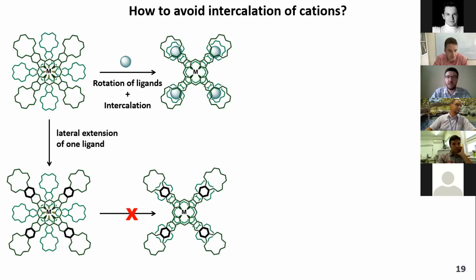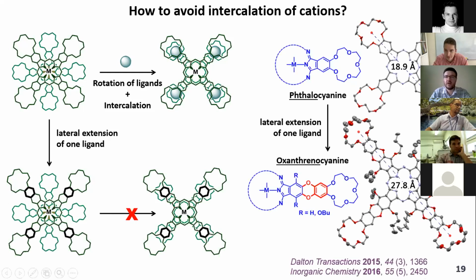With this goal, we decided to use two types of crown-substituted ligands. One of them is the well-known crown phthalocyanine, and another one is crown-substituted oxanthrenocyanine. This type of molecules recently came from our lab, and they showed numerous interesting photophysical properties. You can see that the distances between centroids of opposite crown ether rings are very large in the case of oxanthrenocyanine, and they are much smaller in the case of common phthalocyanine. So no way they can overlap with the formation of sites for intercalation of potassium ions.